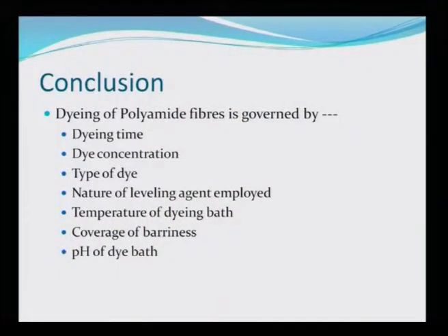So, if we have to conclude, we will say dyeing of polyamide fiber is governed by the dyeing time, the dyeing concentration, the nature of the dye, the type of the dye, nature of leveling agent employed, temperature of the dyeing bath, coverage of barriness, and pH of the dye bath. You see, unless and until these factors, that is the dyeing time, you know, it is not a fast process. Adsorption, diffusion, retention, and then, you know, to break this equilibrium all requires time, and therefore, the dyeing time is very important in the case of polyamide fibers.